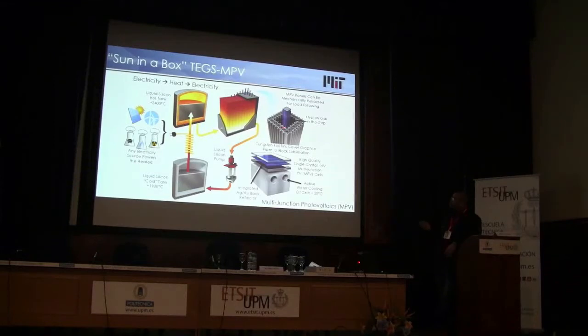In between, we have a tungsten layer. This tungsten layer is very important. I've drawn it with fins here to indicate that we could actually increase the surface area by putting tungsten foil to increase the amount of surface area. There's a reason we want to do that. But the reason the tungsten is there is effectively to act as a diffusion barrier.